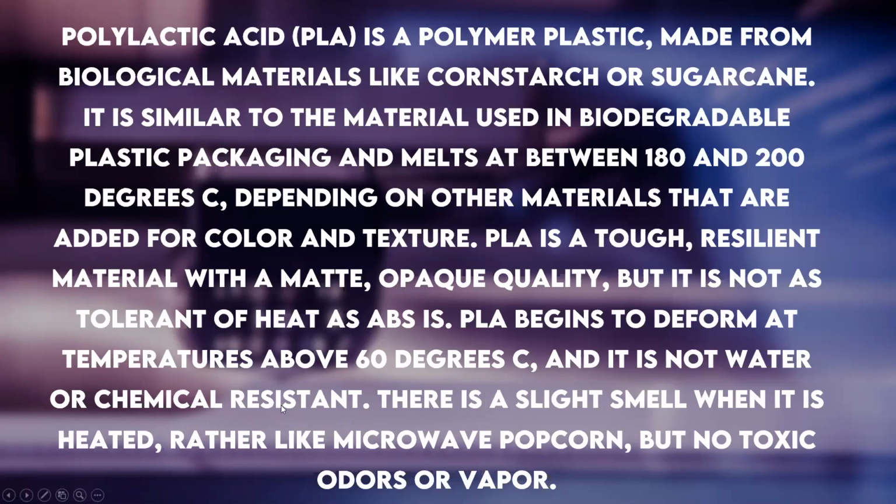PLA is hygroscopic, so it absorbs water from the atmosphere. Long exposure of PLA to the atmosphere will lead to breaking of filaments and popping sounds coming out of your 3D printer because of the water evaporating. So it's not good for a 3D printer to use old PLA or moisture-absorbed PLA.